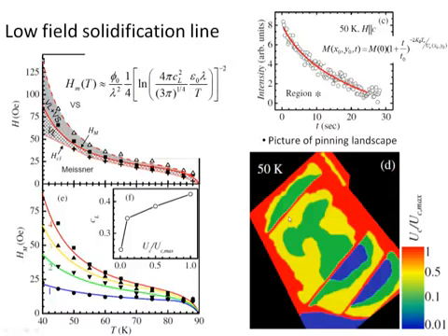The variation in pinning across different regions of the sample are represented by the colored bar present beside the color image of the sample. We find that the location of the low field vortex liquid to solid phase transition boundary shifts with variation in pinning, which is well described by the effective Lindemann number increasing with the pinning strength.